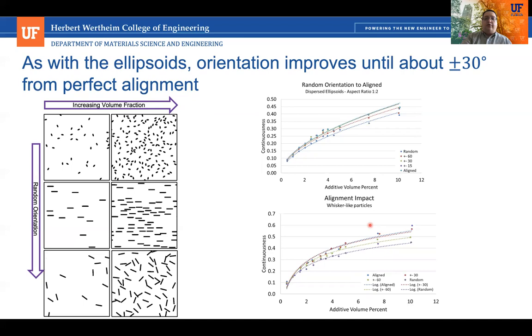So it is very useful, and you can help maximize the thermal conductivity by aligning your additive in the direction of heat transport, but only up to a point, and then you don't have to have full alignment.